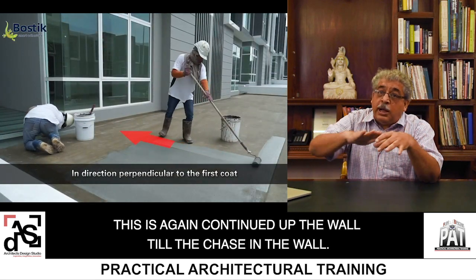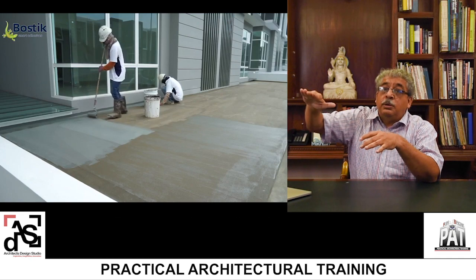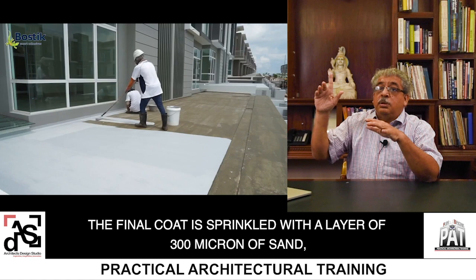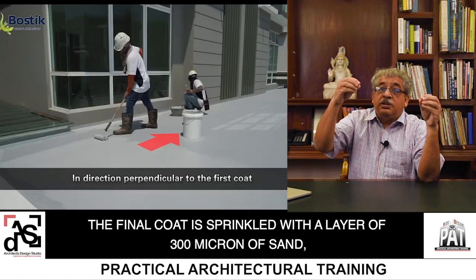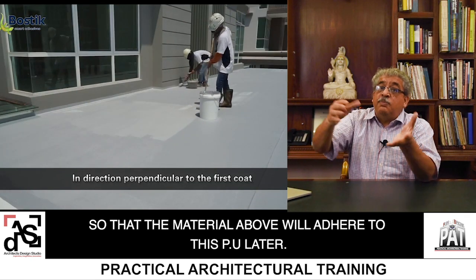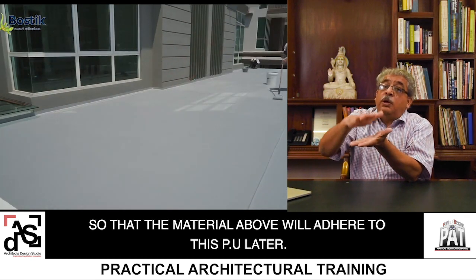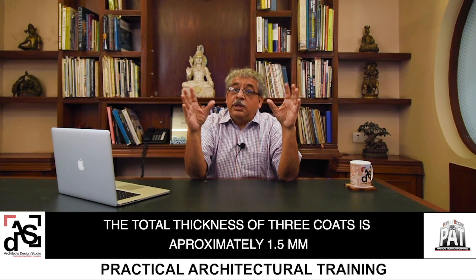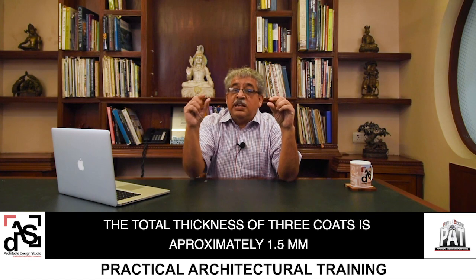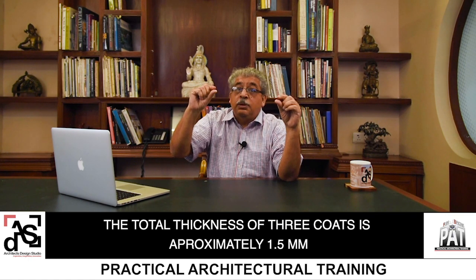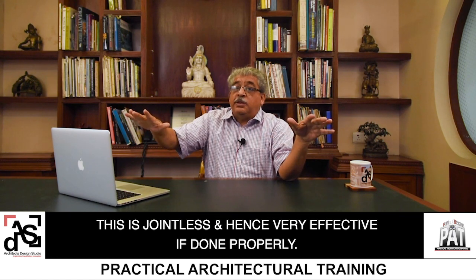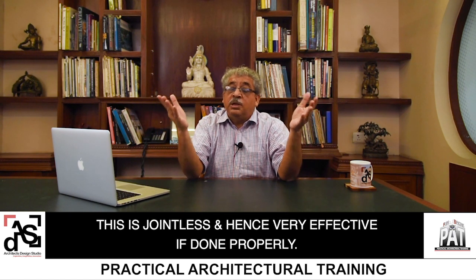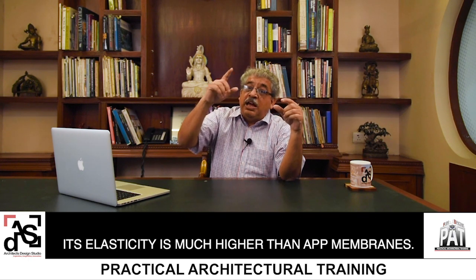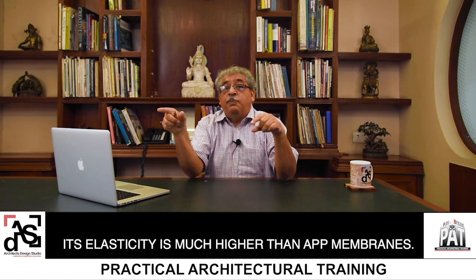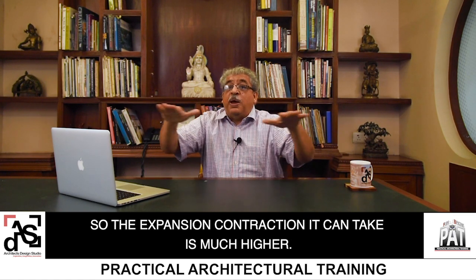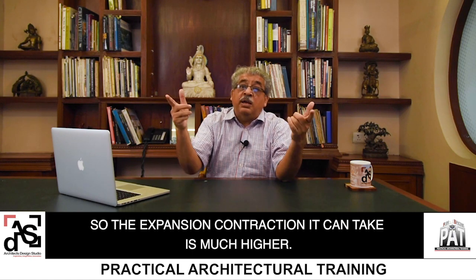This is again continued up to the wall, up to the chase in the wall, and the final coat is sprinkled with a layer of 300 micron of sand so that the material above will adhere to the PU later on. The total thickness of 3 coats is approximately 1.5 mm. This is a jointless method, hence very effective if done properly. Its elasticity is much higher than APP membranes, so the expansion and contraction it can take is much higher.